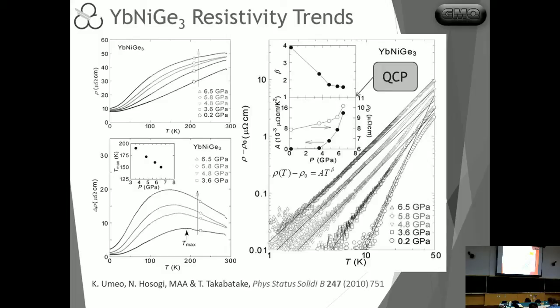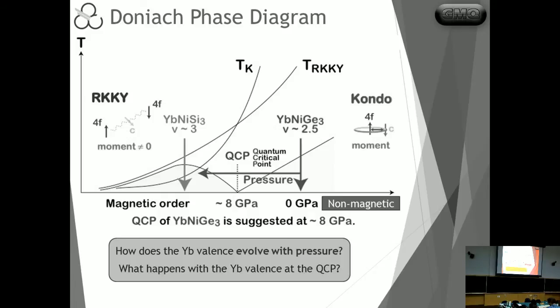So that's what we did later on, still in Hiroshima. And at that time, again, we had a limit in this case of about 7 GPa, and so we couldn't quite get to where we would like to, so we can see the quantum criticality directly. But by looking at how the parameters were evolving in this direction, we could make a prediction that there should be a quantum critical point at around 8 GPa, just a little above where we could go with our instruments. So after that, we were able to interest some people to look at this, some Japanese collaborators, who could go to higher pressures and so on.